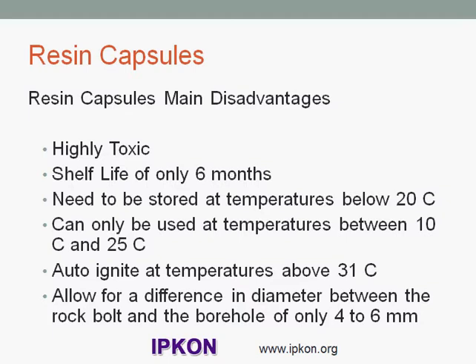They constitute a fire hazard and can auto-ignite at temperatures above 31 degrees Celsius. They allow for a difference in diameter between the rock bolt and the borehole of 4 to 6 millimeters.